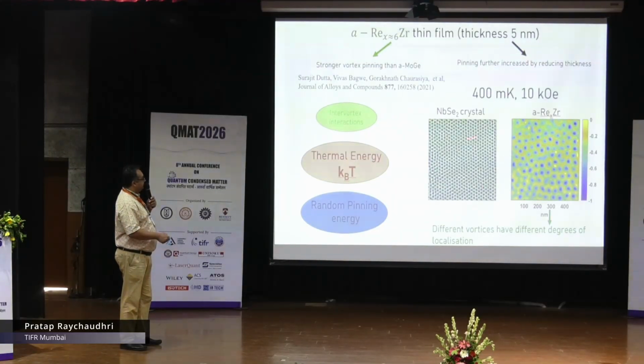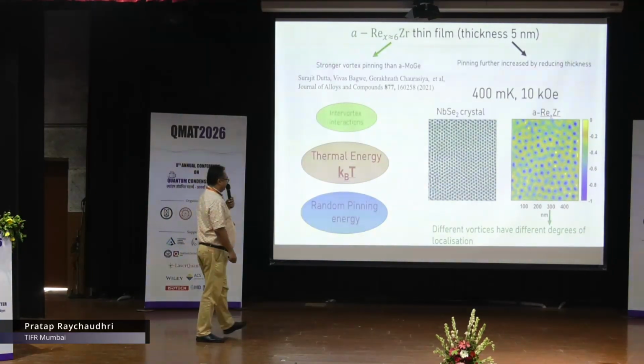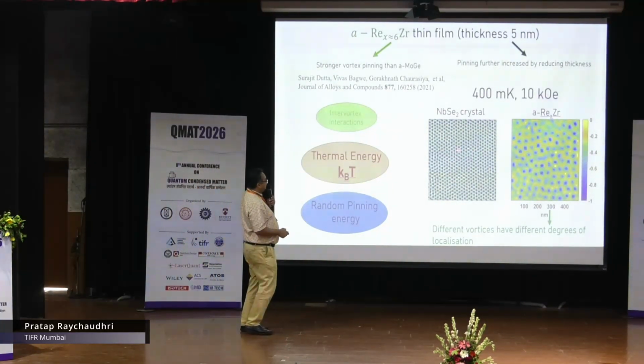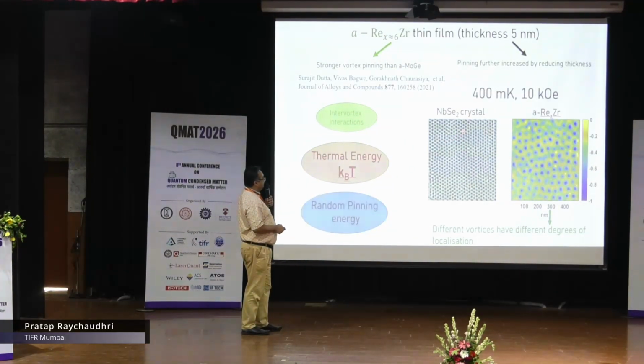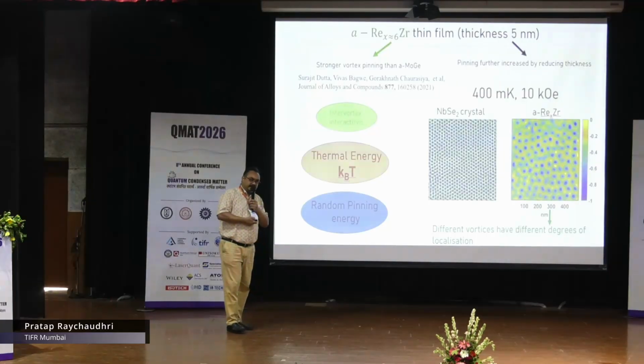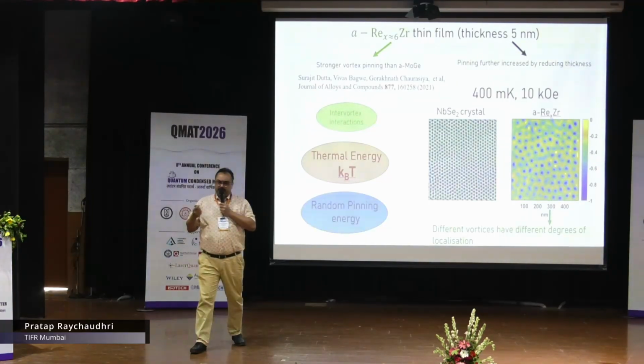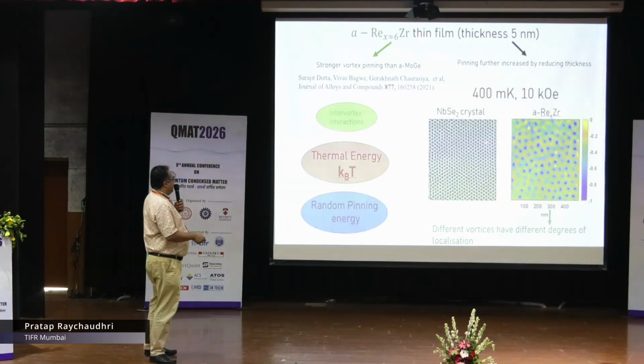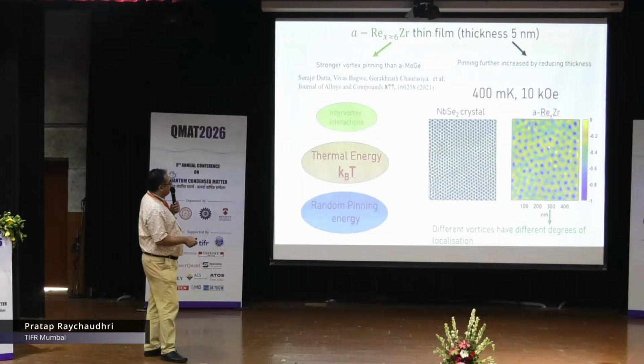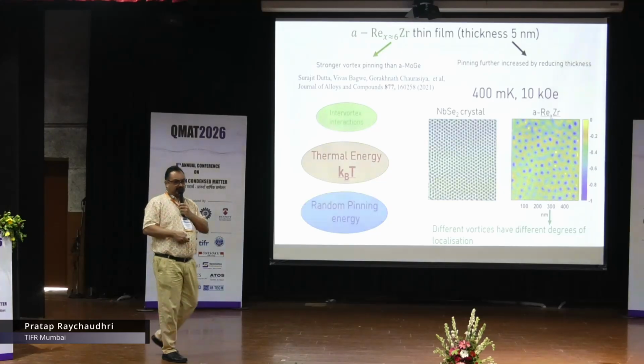And here what I am showing you are the conductance maps in the vortex state for a niobium diselenide crystal and amorphous rhenium zirconium at the same temperature and magnetic field. The striking difference is this. Here you see the conductance minima corresponding to every vortex look almost identical. And that is what is expected. Every vortex is identical. However, here you see some of these minima are extremely deep and some of these minima are very shallow.